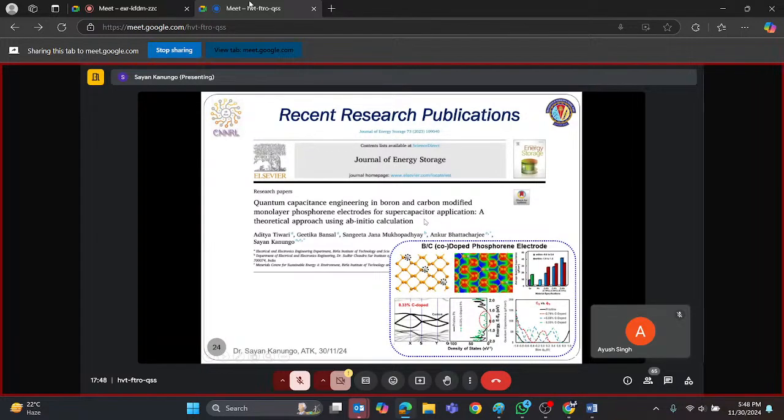So in this specific work, we have particularly focused on boron and carbon doping and co-doping strategies, and our investigation revealed that the introduction of carbon doping is highly advantageous for the overall ideal supercapacitor electrode performance improvement. Specifically, the introduction of carbon leads to delocalized defect states near the Fermi level of the black phosphorus, which essentially transform into a large peak in the low applied local electrode potential range of carbon doped phosphorene.